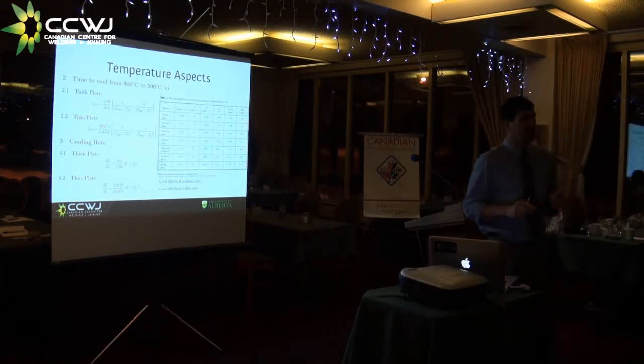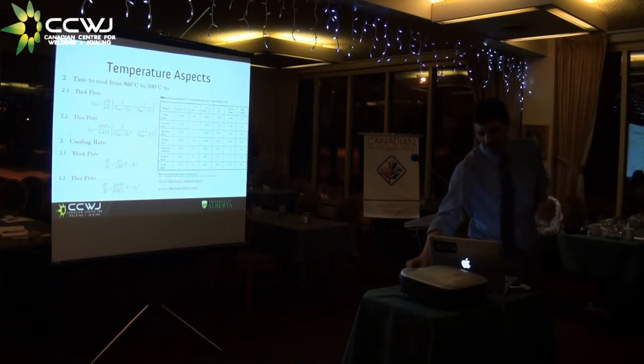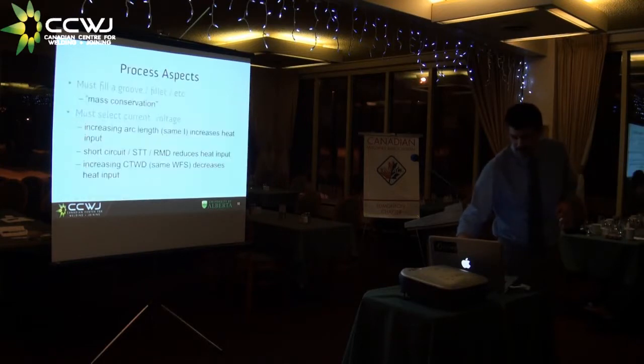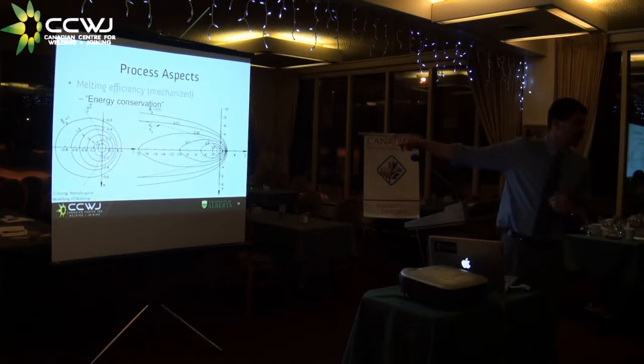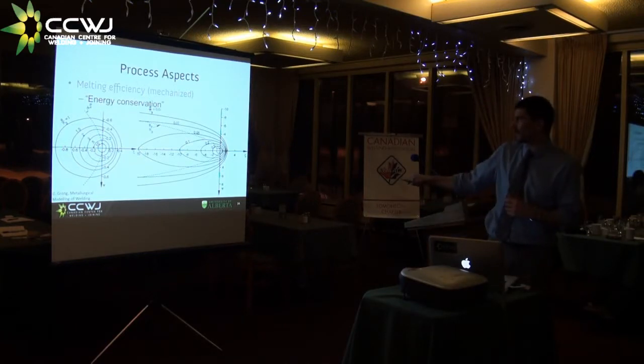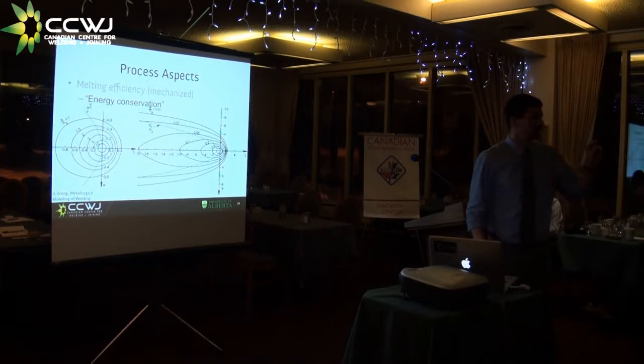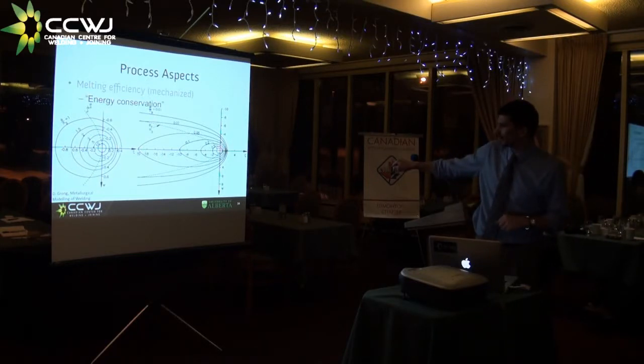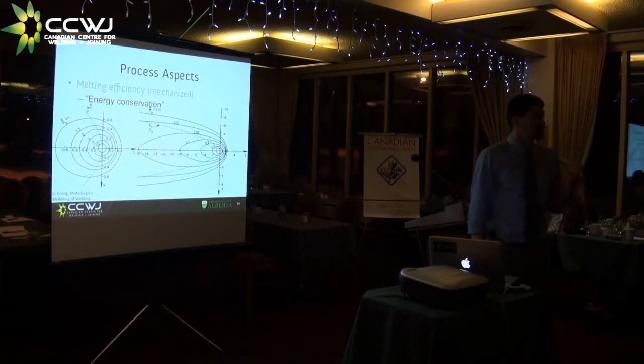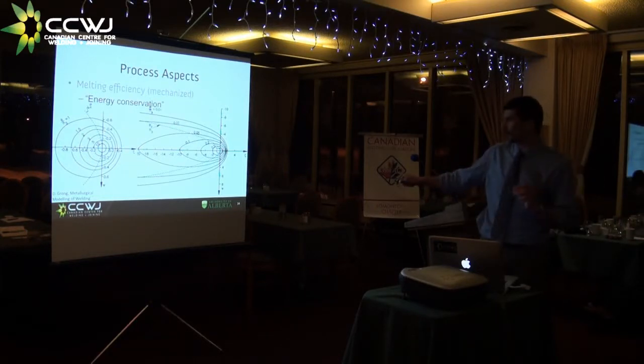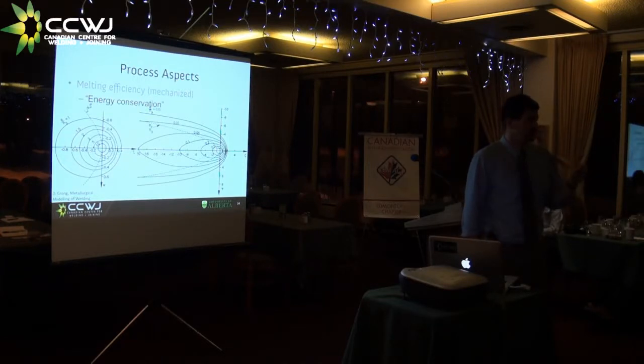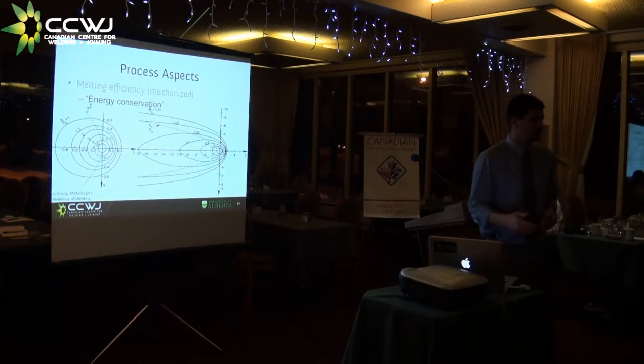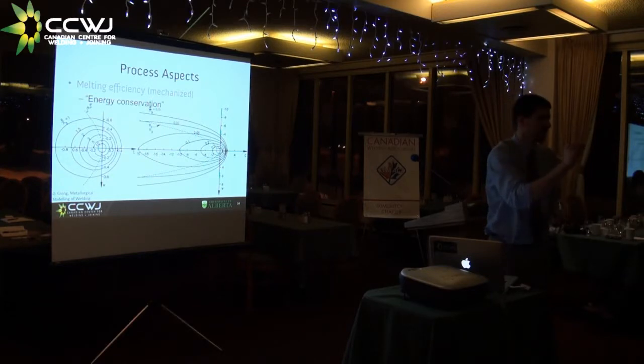Yeah? How thick do you think is thick plate? Oh, excellent question. Okay, this has been very studied. But the criterion is this. If you do the isotherms, let me show you. You see these curves of isotherms? If you care about an isotherm that is longer than the thickness of your plate, wider than the thickness of your plate, then you're working with a thin plate. If you care for an isotherm that is smaller than the thickness of your plate, then it is a thick plate. The bottom line, if you do t8/5, you almost always end up using thin plate, even if you're welding half an inch plate, for the most part.